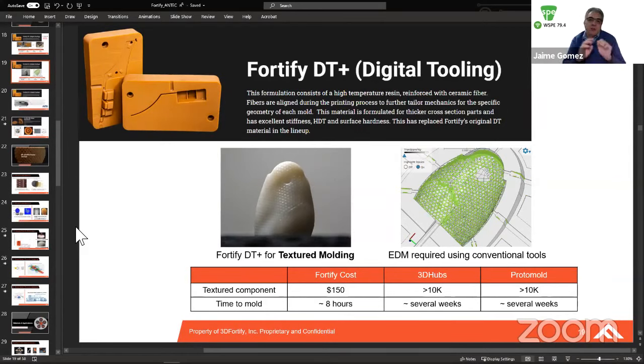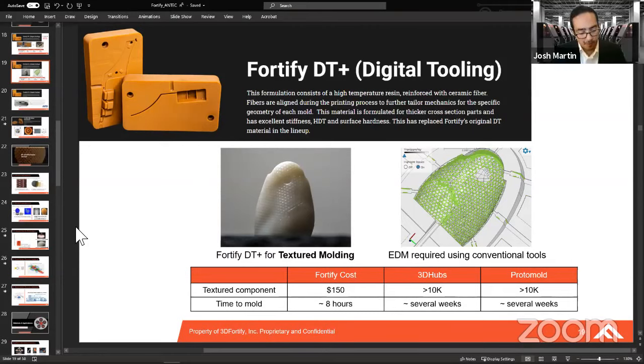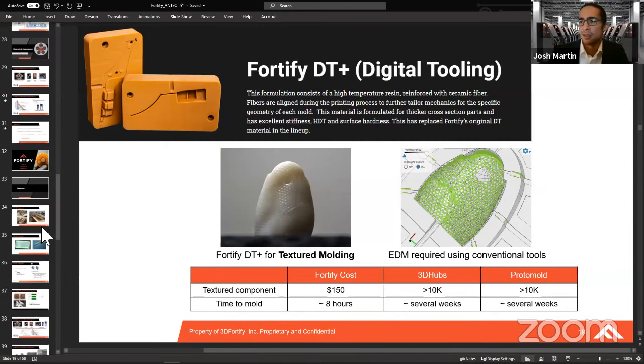Okay, let me talk about durability. You get a part that has been 3D printed. You have a part that has been done by traditional methods. Do you expect longer lifetimes for these complex parts due to lower residual stress? Yes. And so a couple ways to take that. Versus a thermoplastic, from a longevity perspective, we're doing a lot of testing now. Certainly versus most thermosets, we feel that we're at an advantage, especially 3D printed thermosets, because these additives work as a light absorber. They're not necessarily going to allow your part to age from UV as quickly.